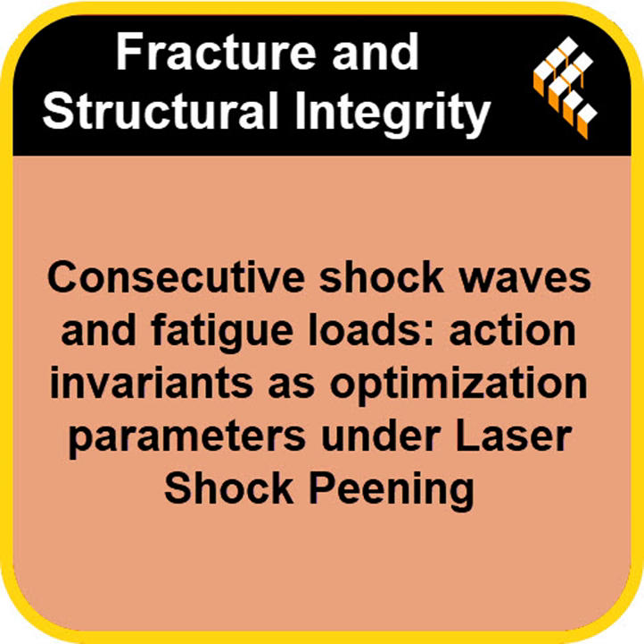It's a fundamental shift. And the really provocative thought here is the universality of it all. The fact that these two incredibly different processes, a nanosecond shock wave and fatigue over years, seem to obey the same underlying fourth power self-similarity law. It hints at something profound about how materials organize themselves on the path to failure. A universal rule for breaking stuff. Maybe. This focus on non-local collective defect behavior captured by these invariants is likely essential if we want to design materials for the next generation of truly extreme service life requirements. It's a whole new way to think about fracture mechanics.